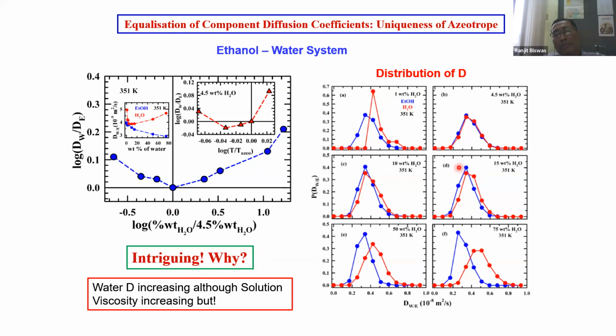Before telling you, let me show you the particle diffusion coefficients. The individual particle diffusion coefficient is simulated and the distributions found. And you see, very interestingly, at 4.5%, they are merging onto each other. They are approaching, and then at 4.5%, you further lower the water content, and they are differentiated, separating from themselves. So we thought this could be a very good signature, a mixed dynamical signature of the formation of the azeotrope.